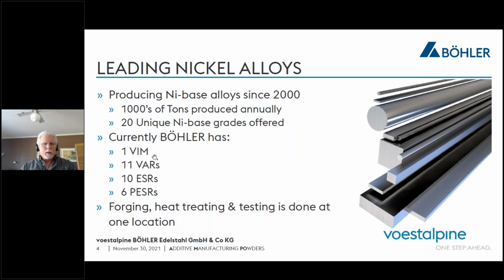Nickel alloys must be produced quite differently from steel. Whereas steels are typically made from iron ore in a basic oxygen furnace or from scrap in an electric arc furnace, modern nickel alloys for the most demanding applications are melted in a vacuum induction furnace and then remelted in either an electroslag remelt furnace or in a vacuum arc remelt furnace. Böhler produces thousands of tons annually of nickel in this way in about 20 unique grades, 718 being one of them.